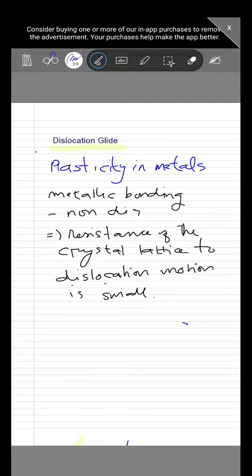Most ceramics fracture before they plastically deform, at least at room temperature, because of the bonding and the complexities in the ceramic crystal structure. Dislocation glide is difficult in ceramics. It is mainly predominant in metals. Atomic bonding in ceramics is either covalent, or ionic, or a mixture of both. Dislocation glide in a covalent material is difficult because it requires breaking and bending of strong directional bonds.